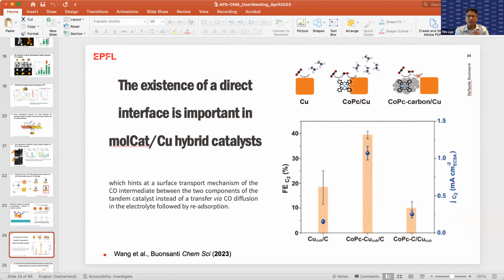So if this catalyst lies flat on a copper surface, for example, you could imagine a pretty strong electronic interaction that could totally change the charge density on the cobalt. Yes, we didn't go into that. This was just a first proof of concept. But of course, it would be nice to start studying the assembly, for example by changing the loading, and looking more carefully into this type of interaction. NMR could also help us determine the arrangement of the molecule, or see if they arrange differently on the 111 surface or the 100. So there are more experiments to do, actually. In fact, you could probably do a Raman measurement, since this molecule will probably be enhanced on a copper surface. Yeah, that's also a good idea.